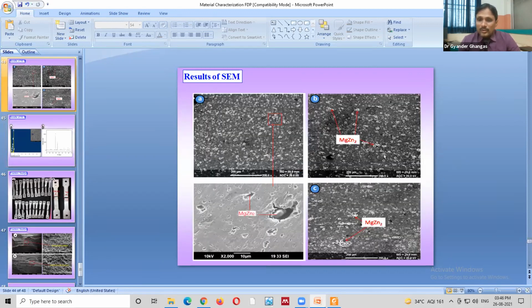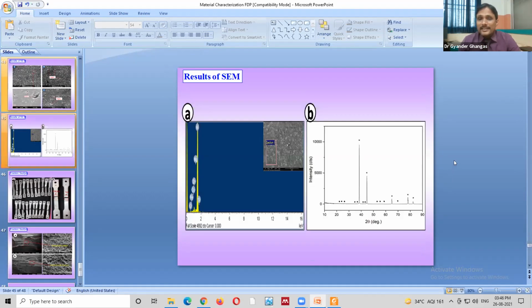But still we don't know whether these precipitates are MgZn2, so we performed EDS on the SEM and XRD on the XRD setup. EDS on the SEM provides the elemental information, such as the presence of aluminium, magnesium, zinc, copper, silicon, iron, oxygen, etc. But the XRD provides information about the presence of MgZn2 with the help of these peaks. We matched, or interpreted, this data with the help of standard data provided by a standardization agency. So we found those were MgZn2.